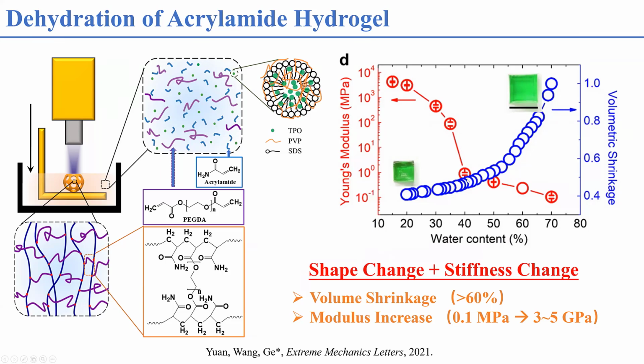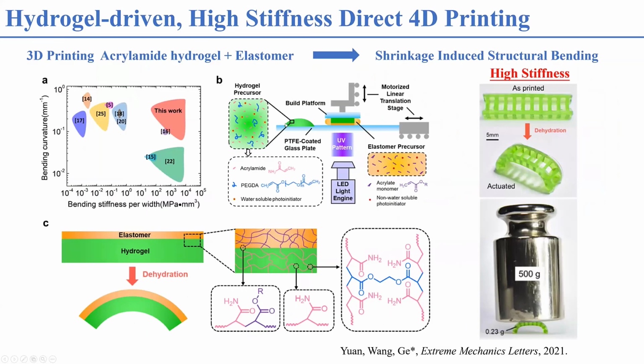And then we use this, combined with our multi-material 3D printing system. We print hydrogel with elastomer, and once the hydrogel loses water, it will create a bending. If we design some structure, we can make a 2D structure become a 3D structure. But also, as I mentioned earlier, there is not only shape change, but also stiffness change. The printed structure can also carry heavy load.